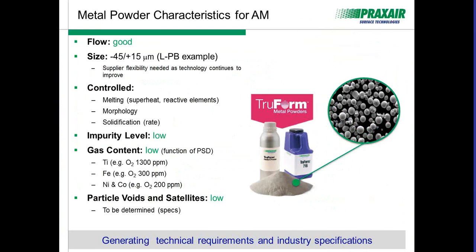When you look at literature and read about powders, you'll hear things like satellite particles, which physically means a smaller particle essentially welded to a larger particle, looking like a satellite that's frozen in place. It can also have dimples on the surface and irregular shapes. A lot of that comes back to how you're atomizing, the ratio of gas, think of it as pounds of gas per minute versus pounds of liquid metal per minute. As we modify that, we can change the surface characteristics and the particle morphology.